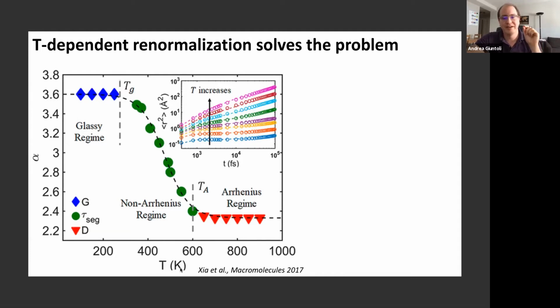In particular, for very high temperatures, you can match the diffusion constant. Then for the intermediate temperature regime, you can match the alpha relaxation time, tau. And then if you go below the glass transition, you can match, for example, the shear modulus. Now, this is a crazy effort they did. It's very good. But if you think about it now, the diffusion constant is related to the Debye-Waller factor at high temperature. The alpha relaxation time is related to the Debye-Waller factor.